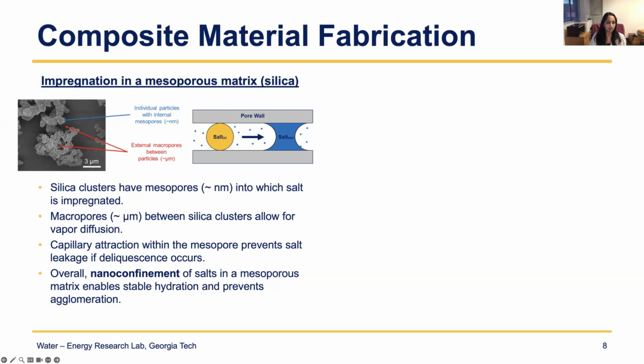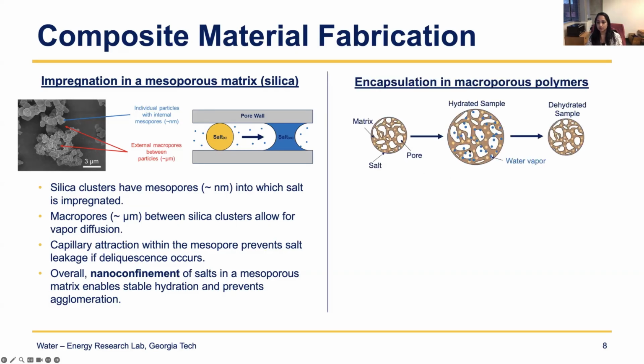And then between the silica particles, we have larger macropores where water vapor can transport in and out. So essentially, we nano-confine the salts in a mesoporous matrix and allow the water vapor to transport. So this gives you a very stable composite that you can cycle hundreds of times. You can also form these types of encapsulated structures.